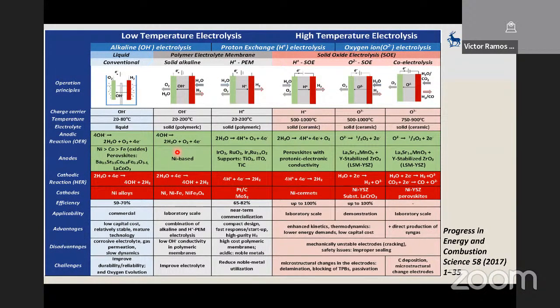The conventional one is liquid, it's alkaline, which is very established, but has a fairly modest efficiency. It's about up to 70%. 30% of the energy is actually lost, whatever energy you put in, solar energy or wind energy. But there's a promising proton exchange membrane. It's the solid state membrane technology. For those who are familiar with this technology, it is very promising. It's an early stage commercial demonstration, and can go up to 82%.